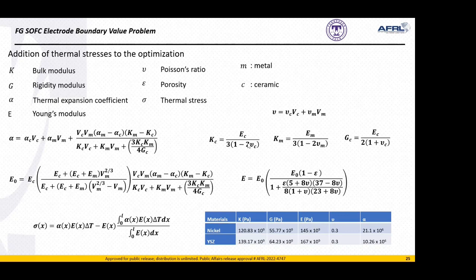And here I just want to show a sample of doing some of this analysis for a functionally graded nickel and YSZ electrode. So if we use the 3D printing process and we print using these concave down profiles of varying degree up to a linear profile, you can see here on the bottom a graphic representation of that microstructure. The thermal stresses that result are shown in the right-hand graph. Positive stresses are tensile and negative are compressive. So we get a bending moment as a nickel-rich surface has a higher thermal expansion coefficient than the YSZ. It's again trying to delaminate, pull itself off of the electrode.